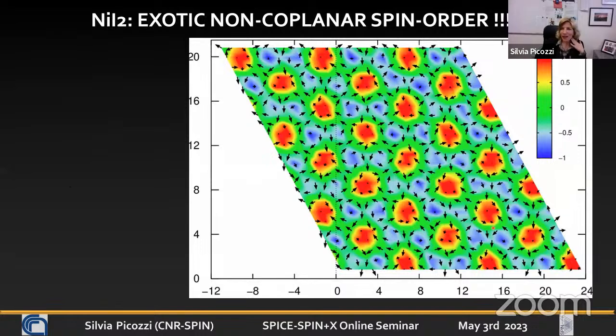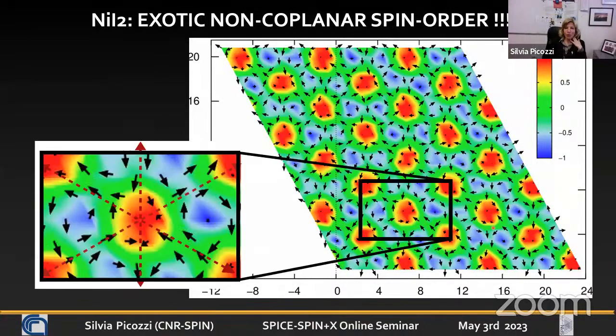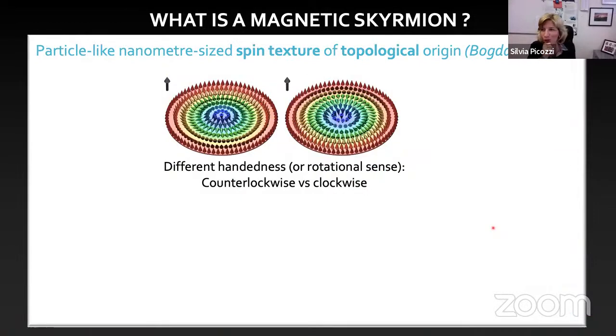What we didn't expect was what we got for nickel iodide. Because for nickel iodide, we got something like this. And so you basically see there is a lattice. It's a complex spin order. And at that time, we were not at all experts, still we are not. But we could recognize that this was a kind of skyrmionic lattice. So I'm sure there are experts in the audience about skyrmions, so I'll be rather fast on this.